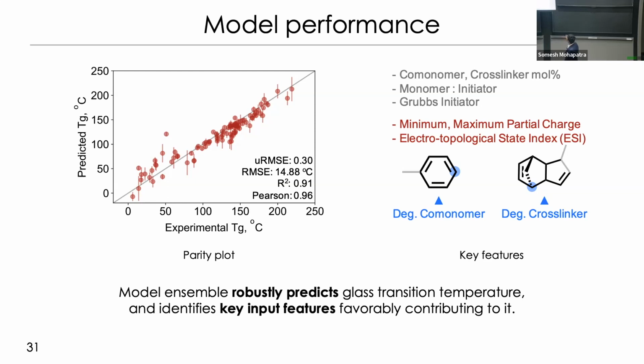But the model also said that it was looking at the partial charges and the electrotopological state index. Some help from Yasmin came in there, and there was an understanding that maybe there's a zwitterionic system being formed. There's a positive set of charges and a negative set of charges which are coming close and decreasing the free volume, and hence increasing the density and increasing the TG. And when it does that for an aryl substituent in a comonomer, then there's pi-pi stacking and a decrease in the free volume there. So the model was doing something on its own basis and finding features that help it make the decision of predicting TG reliably.